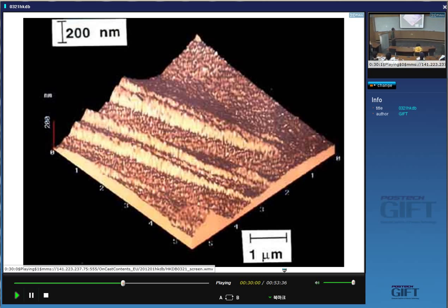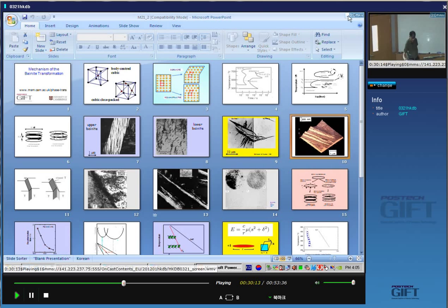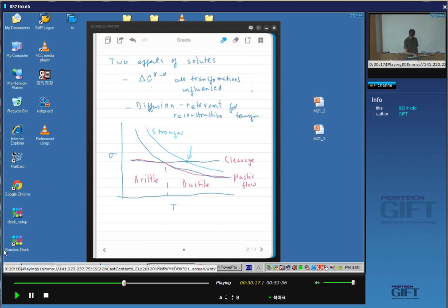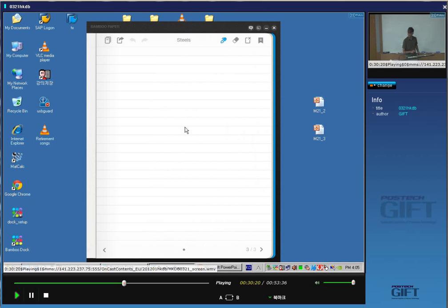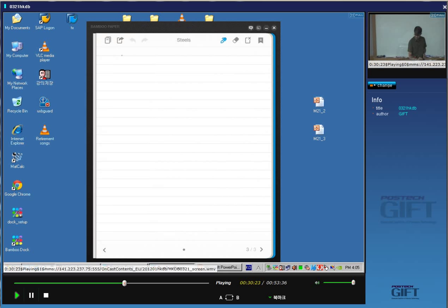This is the adjacent austenite here, and that has relaxed. Can you see that? Remember in the last lecture, I talked about plastic relaxation of the shape deformation. So if we have an elastically accommodated shape change, then you will get a perfect tilting of the surface. And this is the martensite under the surface, so this is alpha, and this is gamma, and gamma. And this is elastically accommodated.